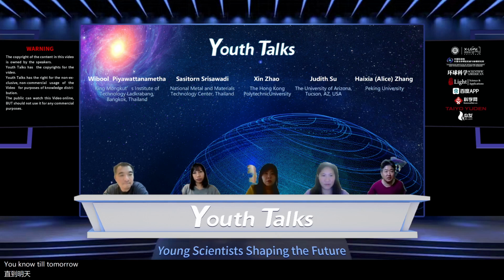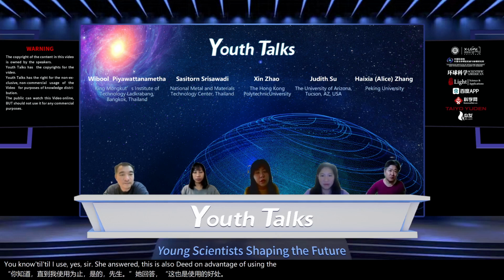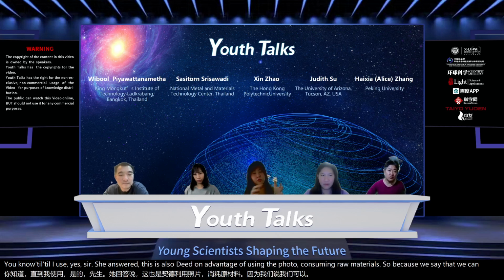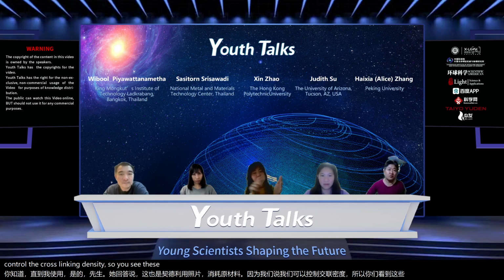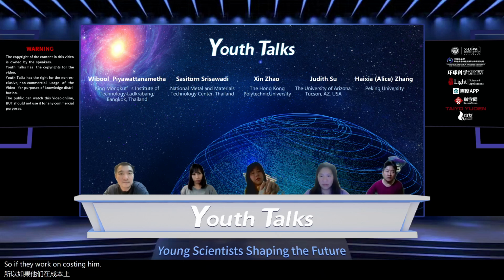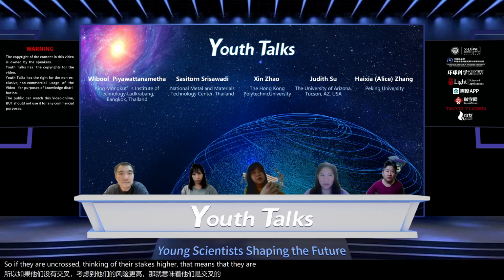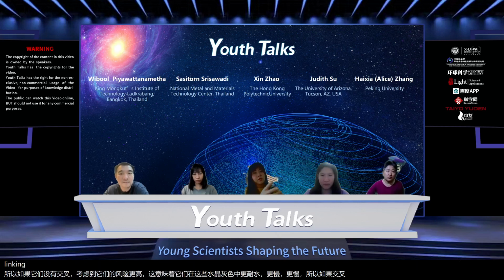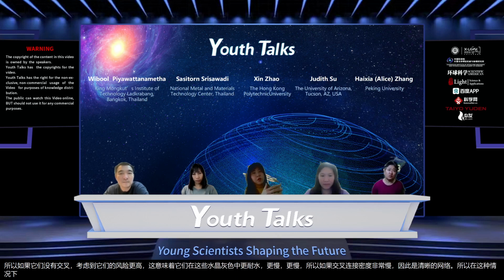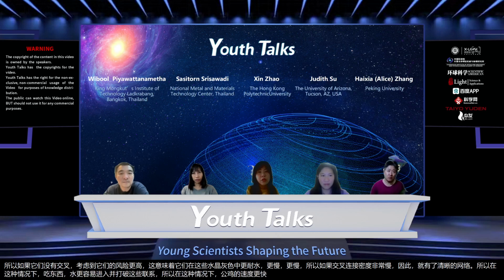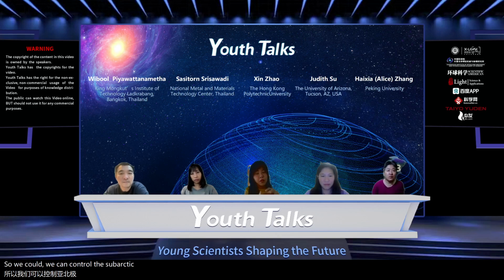Tuned by use? Okay. Yeah, so this is also the advantage of using the photocrosslinkable material. Because we can control the cross-linking density. If the cross-linking density is higher, that means they are more resistant to water. In this case, they degrade slower. If the cross-linking density is lower, they've got a looser network. In these cases, water can more easily come in and break those bonds, so they will degrade faster. So by controlling this cross-linking density, we can control the degradation rate.